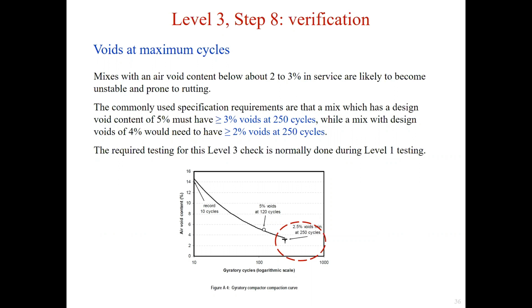A mix with design voids of 4% would need to have greater or equal to 2% voids at 250 cycles. We could take measurement, work out the air void at 250 cycles, and check if it meets the above requirement. This air void check is normally done during the level 1 testing.